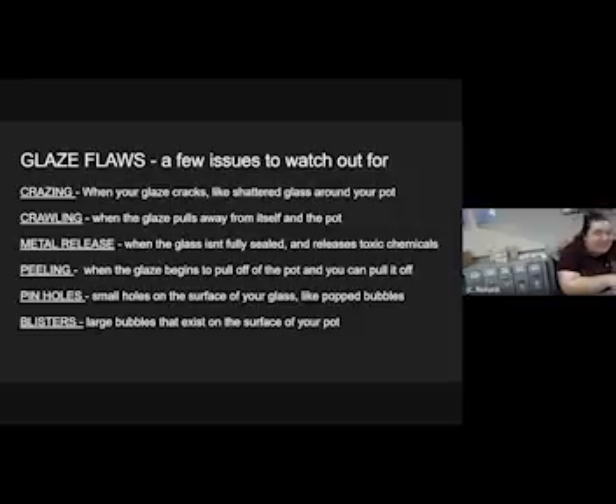and I actually challenge each of you to sort of test this out on your stuff at home. And the way we test it is very, very simple. When the glaze isn't fully sealed, it will release toxic chemicals. This is why they sometimes recall certain products after they send them out. So what you can do to sort of test this is get a lemon, something with an acid in it, and just squeeze it into the bottom of your cup and let it just hang out for like a day or two. If you see that lemon juice turn any color other than cloudy, then your cup is leaching chemicals.